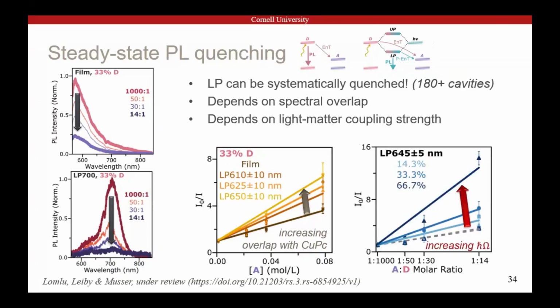But if we sit at one particular spectral overlap position around 650 nanometers and just increase the rhodamine concentration, so the collective light-matter coupling strength, we see that for very weak coupling, it's barely better than the bare films. But as we ramp up the collective light-matter interaction, it gets more and more efficient. So this is a process that is actually sensitive to the collective interaction of all of the molecules with light, which tells us it's something polaritonic, which was kind of exciting, but also really disappointing. Because if you're used to looking at these kinds of plots, you realize we're changing the slope by like a factor of 3, which is incredibly underwhelming for this collective excitation that should span hundreds of thousands or millions of molecules.